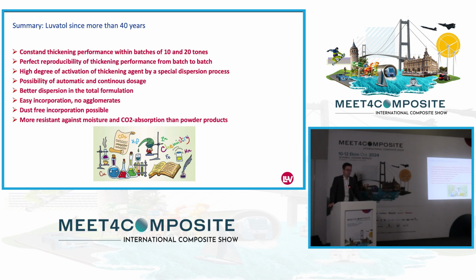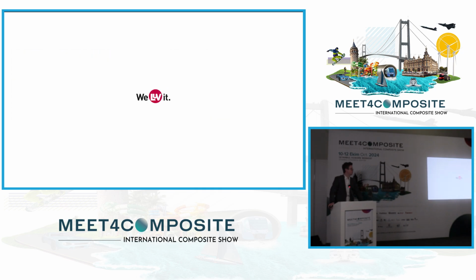And additionally, you don't have the problems with the MgO powder that you normally find, for example white parts, if you produce pure white parts. In every MgO batch, you will find some black dots, which you will find later on also in your final products. That's something you can avoid as well. And of course, it's more resistant against water, because there are also some types which have water absorbent in there. That's the part about the Luvatol.